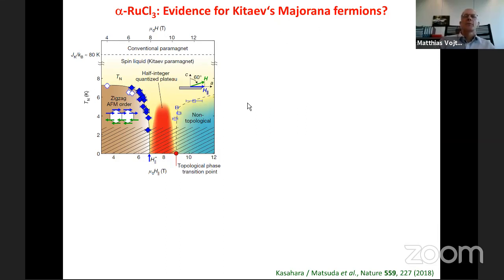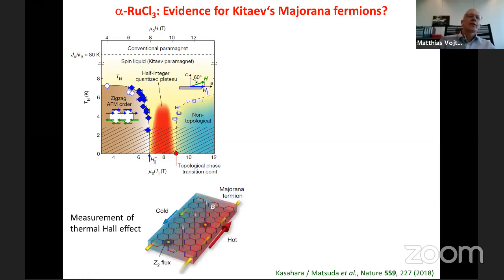This is a magnet which, because it does not only have these Kitaev interactions, but also other interactions, orders antiferromagnetically. What you see here is a phase diagram as function of temperature and magnetic field. There's a magnetically ordered state at low temperatures and fields. But this can be suppressed by relatively small magnetic field, and then there is interesting physics going on. And this experimental observation concerns this red regime here. And what has been measured is the thermal Hall effect. So it's a Hall effect arising from heat carriers. So in other words, you take the sample, you apply a magnetic field perpendicular to it, and then you drive a heat current in one direction, you measure the temperature gradient in the other direction. So that's the thermal analog of the conventional Hall effect.